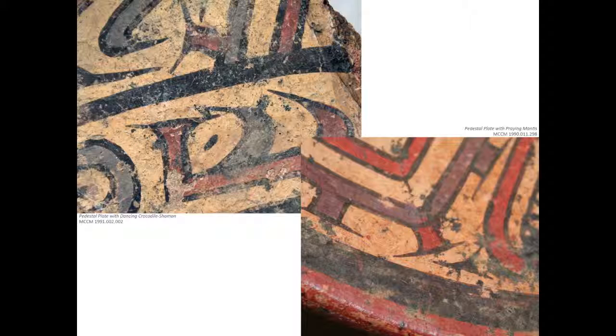If the purple slip was always added first or last, a change in the firing conditions could be possible. However, when the overlap of the various slips is examined, sometimes the red pigment is seen applied over the purple, and sometimes the purple overlaps the red, and sometimes both occur in the same ceramic. Therefore, the hematite must have been turned purple first, and then applied as a slip to the pot.